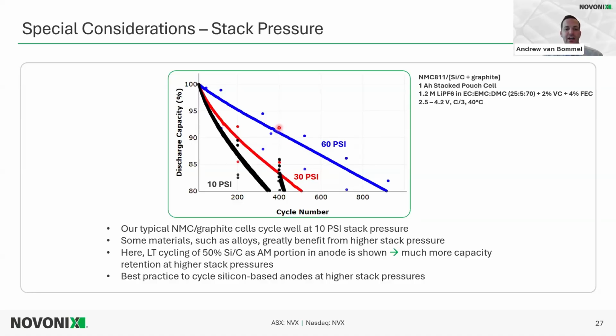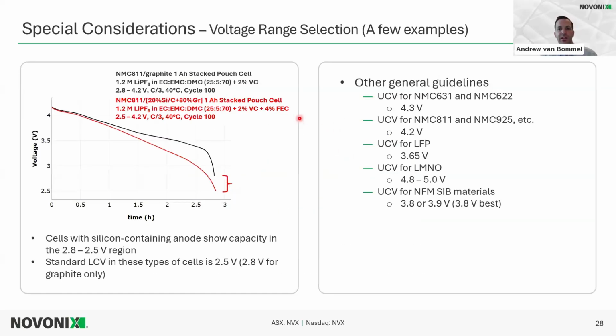So it's best practice when we are cycling cells with silicon-based anodes to have that higher stack pressure. A really important consideration for cycling is voltage range selection. So here are a few examples. Here in black is only the discharge curve for C/3 cycling of NMC 811 graphite 1 amp hour stack pouch cell. And we see that at the end of discharge, there's a sudden drop off in the voltage.